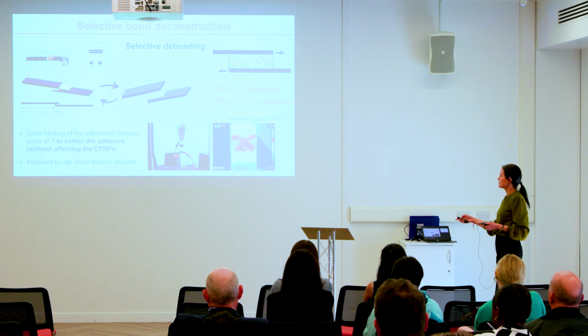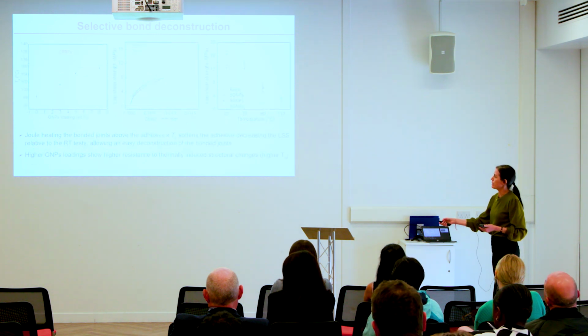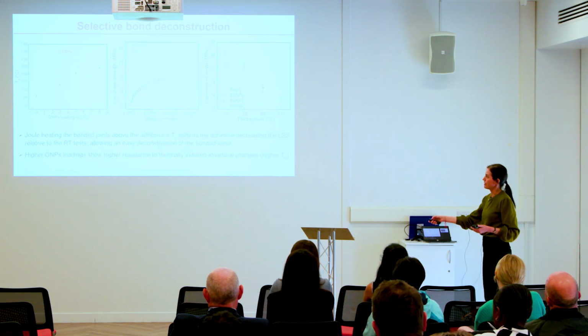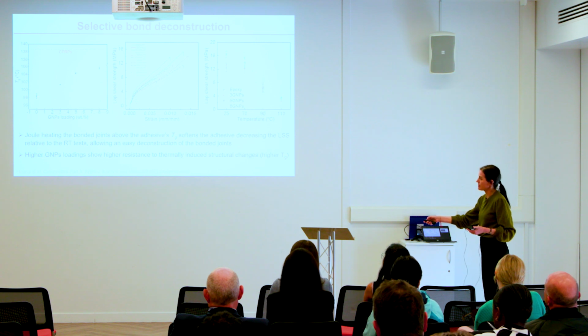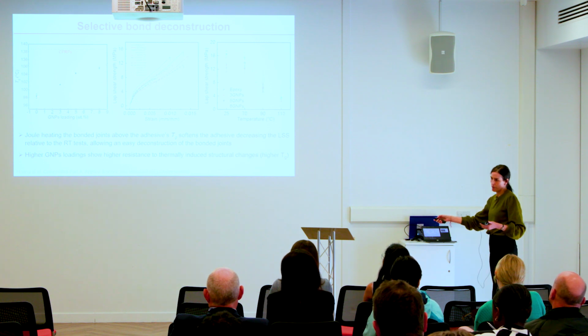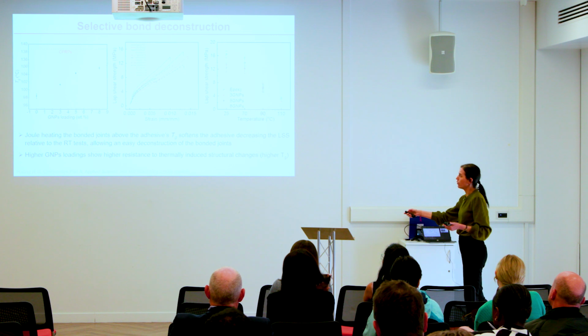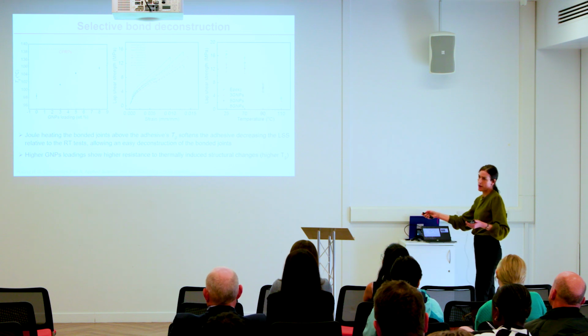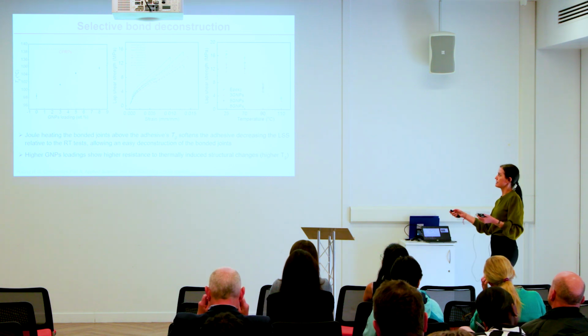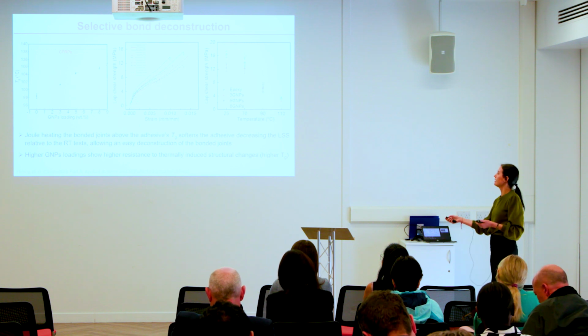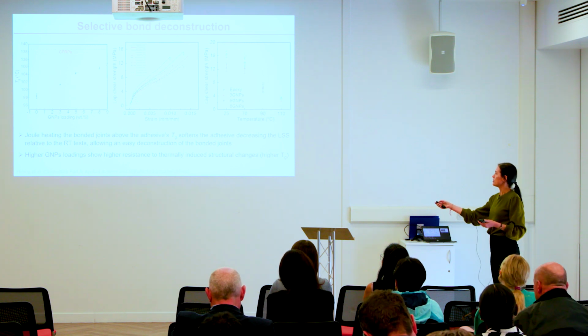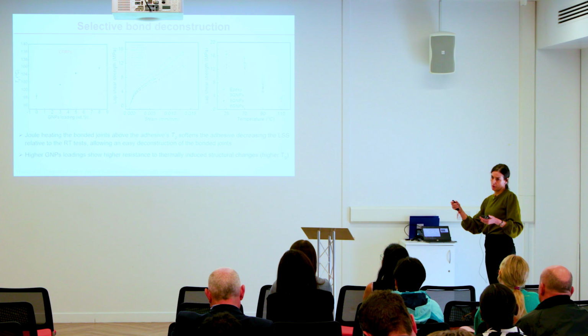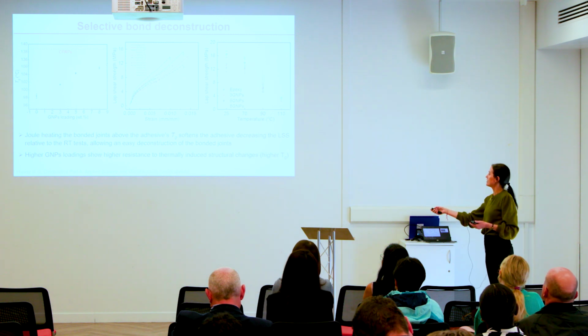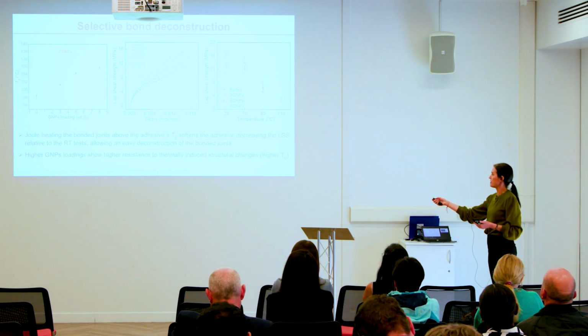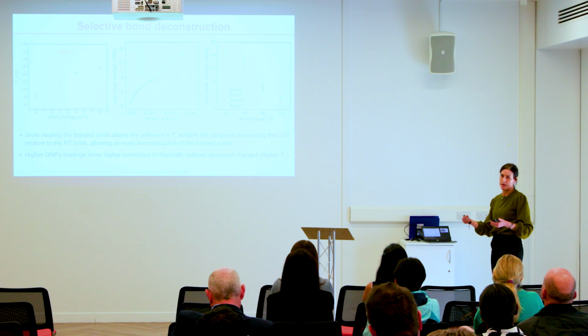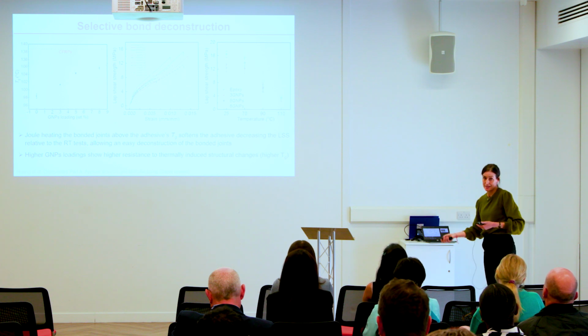Here we see that when we are adding graphene into our adhesive, into the epoxy, we are progressively increasing the Tg. However, in all the cases, we are well below the Tg of the composites, as required for an effective selective bond deconstruction. And here we see that when we Joule heat the bonded joints at increasing temperatures, we are progressively decreasing the lap shear strengths. We are making the deconstruction increasingly easier.